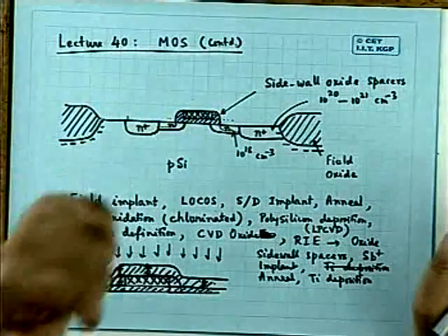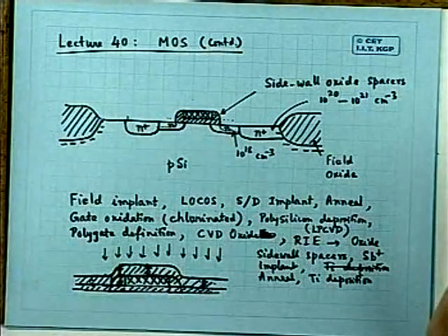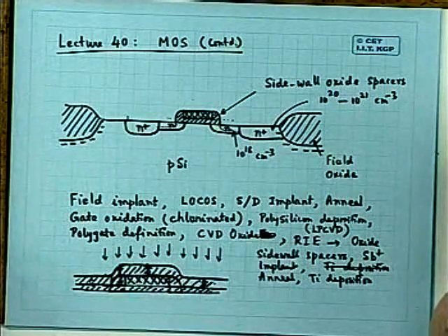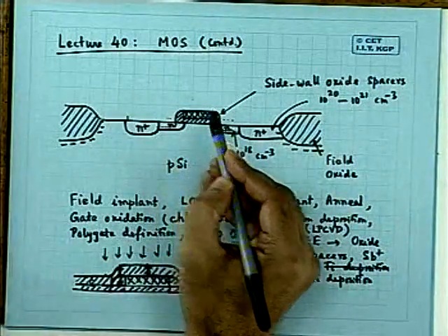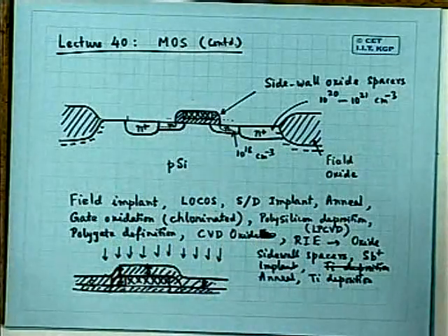What I say is that after titanium deposition, you heat treat it at a temperature around 900, 950 degrees centigrade in a certain atmosphere. Before that also something else is done, okay? And as a result, silicidation takes place, a reaction takes place. So the silicon exposed region, either silicon or polysilicon, gets converted into silicide. Polysilicon converted into silicide is called polyside in the language of technology, whereas silicon converted into silicide is usually called simple silicide. That's how we differentiate between the silicide on polysilicon and silicide on crystalline silicon. It's the usual technological terms.